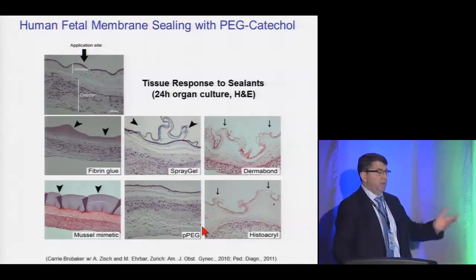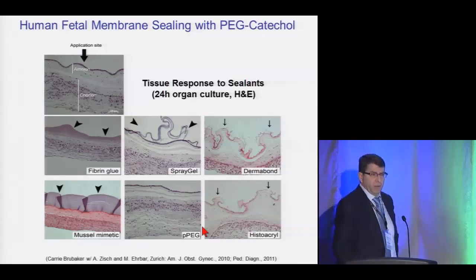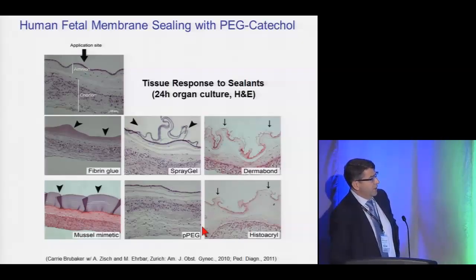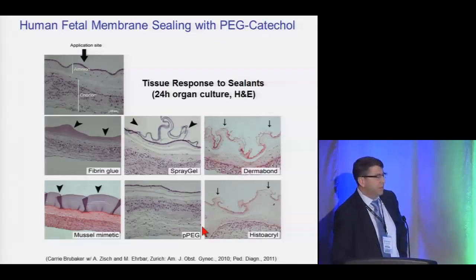Because this is fresh tissue, we can do about 24 or 48 hours of organ culture and look at the very acute stages of inflammatory response through general histology here, and compare it to some other candidate materials. The two on the right are cyanoacrylates, Dermabond and Histoacryl, and you can see a very significant disruption of the tissue here. So it's a very aggressive acute inflammatory response with these materials. The two in the middle here are other versions of polyethylene glycol sealants. They don't seal or adhere to the tissue very well, as you can see. This one actually cannot even be found bound to the tissue after 24 hours.